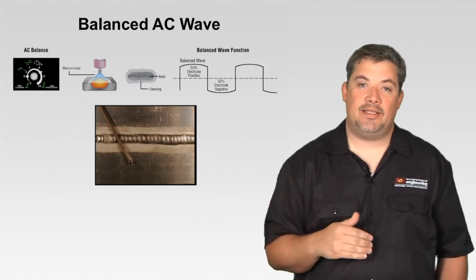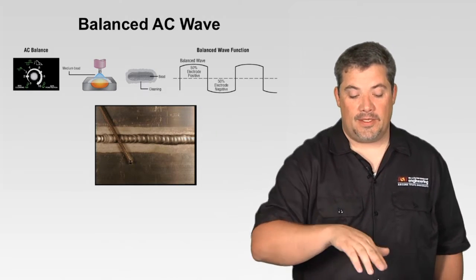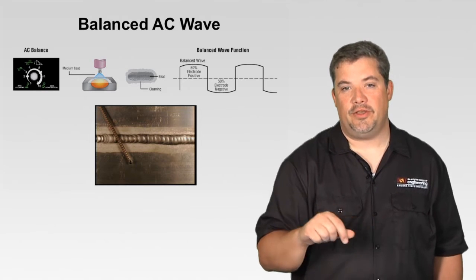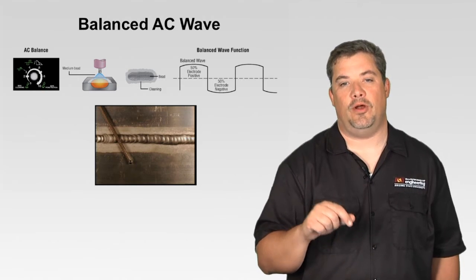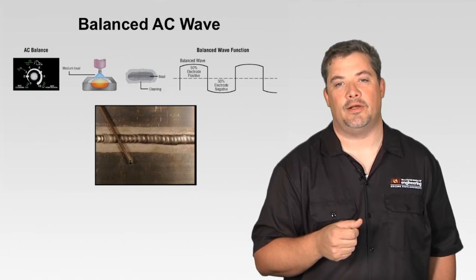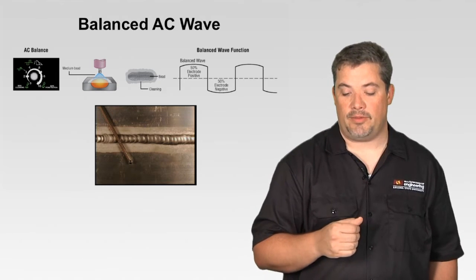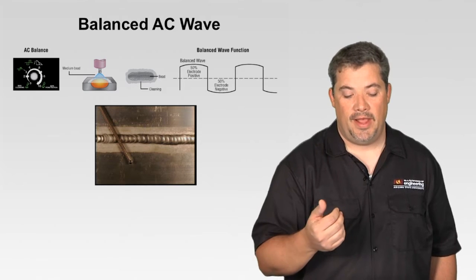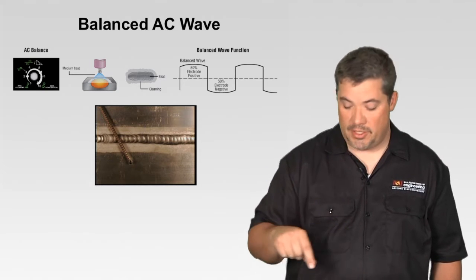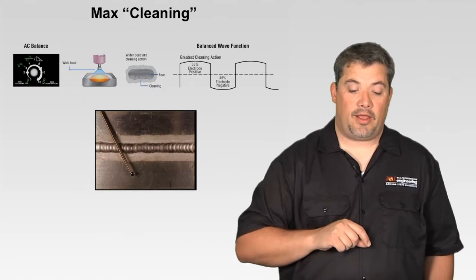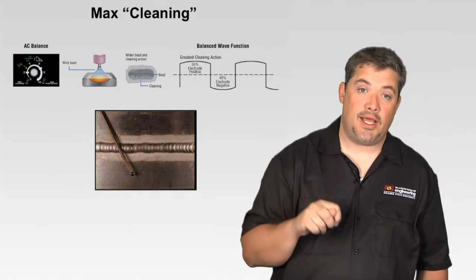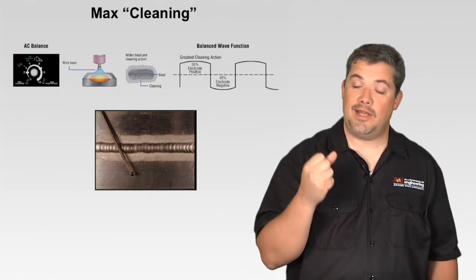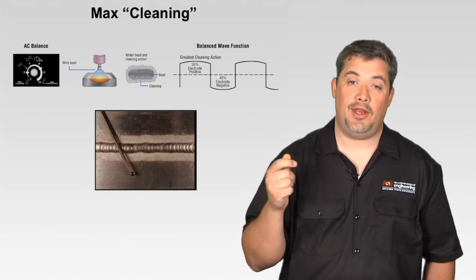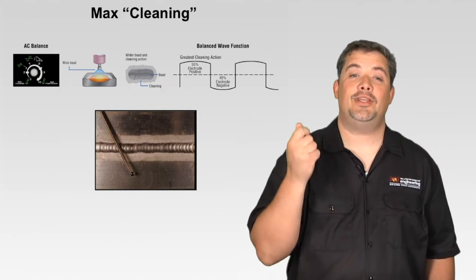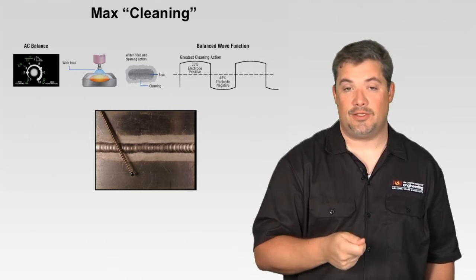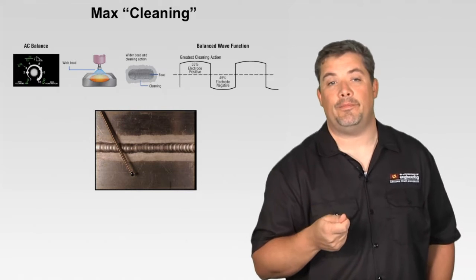Back to that balanced AC wave, in this illustration you can see a lot of white etching along the toes of the weld. You can see a pretty large diameter ball on the tungsten. So 50% of the arc time is positive, 50% is negative, and it makes a medium bead shape. Then on a conventional machine, I can go to this max cleaning setting, where it's not cleaning oil, grease, dust, dirt, or debris. You had to do that prior. This is etching the oxide layer. So that name cleaning is going away, and it'll say maximum etching.